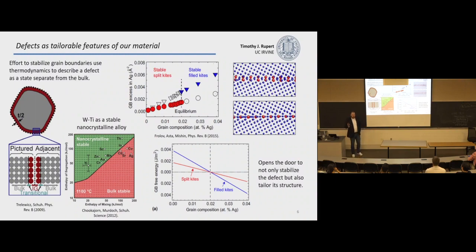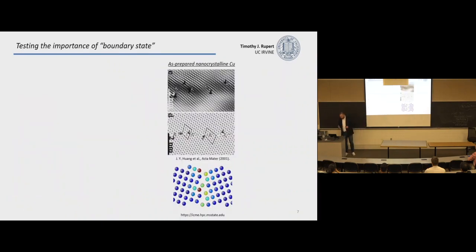But when you do that and you dope those grain boundaries, you also tend to change their structure as well. This is a really simple example. These people were doing a computational study, starting with 2 grains smushed together, 1 grain boundary. As you add more and more, this is silver being added to the grain boundary, you see that the grain boundary excess goes up, but at some point you get a jump in this curve, and then you follow a different slope. That discontinuity is when you have a change in the structure between these 2 types of features. So the concept here is that if you start to add in secondary elements, they go to the boundary, they reduce the energy, and you can also tune the grain boundary structure as well. This is a really subtle example, but there are more dramatic examples you can go after that I'll talk about in a second.